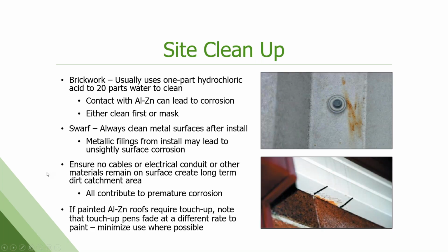Site cleanup. Again, with brickwork and masonry work, make sure you get the mortar, brick, and stonework off the surface as quickly as possible, as soon as it's done. Swarf is metal filings from drill holes or cutting done in the field that are left on the surface. Those little filings rust and leave a stain or can actually embed in the surface of the panels. So make sure you clean those off right away. Once that stain is there, it's really hard to remove.